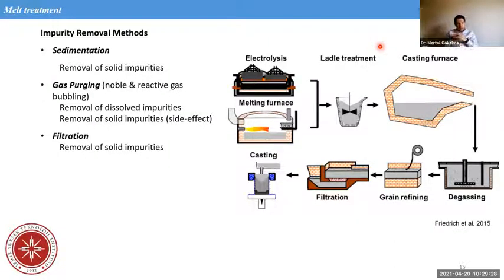And the second one is gas purging. We can do it via a noble gas or a reactive gas. You can see here the degassing and little bubbles, and this is a rotor, a degassing rotor. It homogenizes the bubble distribution in the melt. And if this is a noble gas, then we can remove some dissolved impurities, such as hydrogen. With reactive gas, we can remove alkali metals. But as a side effect, there will always be removal of solid impurities.